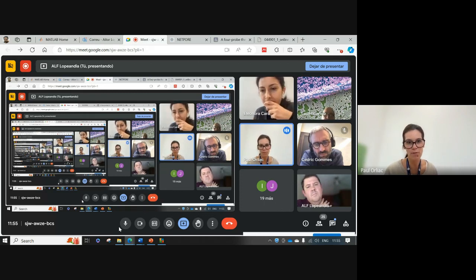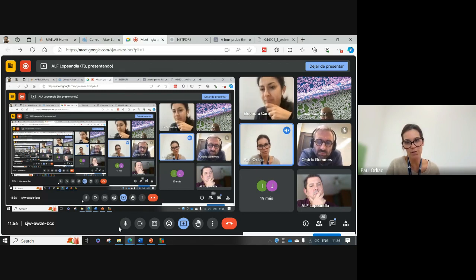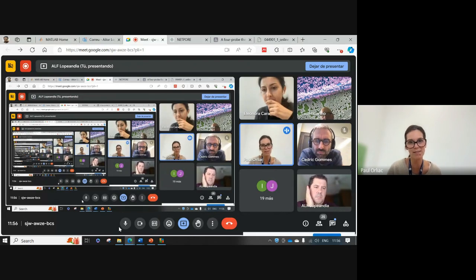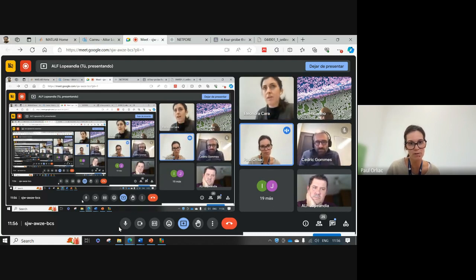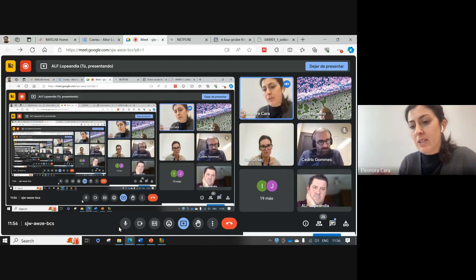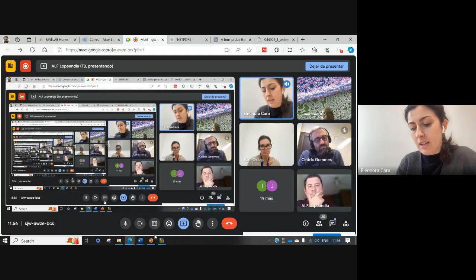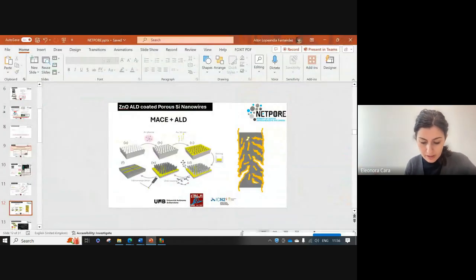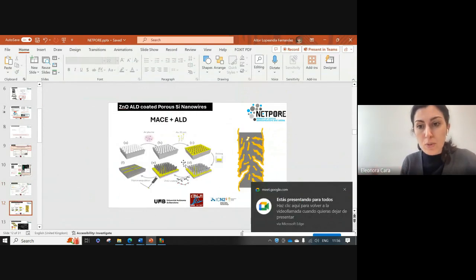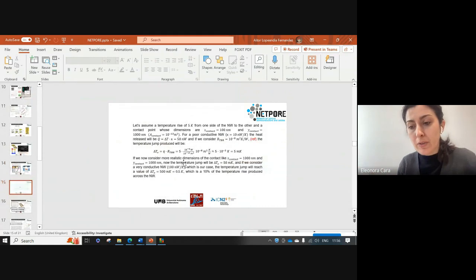If you could envisage the influence of the pore diameter, if there is any, it's pretty much the same approach that I was talking about for mechanical stability, because at some point, if you change the pore diameter, you can fragilize the system maybe, and when you use it, if you have some broken part or open porosity, maybe you lose some contact. I'm not sure. This is pretty related. And the question is, is there a structure that would be optimized for the performance of the system? So I think for sure there is a percolation path inside the nanowire. As Aitor was mentioning, the mean free path is reduced inside the nanowire due to the presence of the pores.